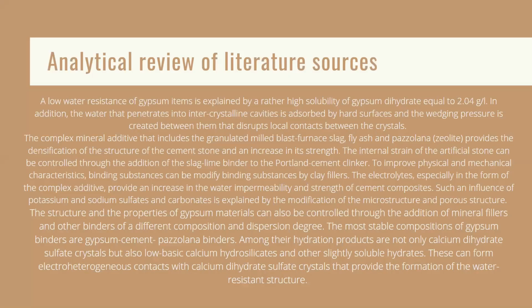A low water resistance of gypsum items is explained by the high solubility of gypsum dihydrate, equal to 2.04 g/l. In addition, the water that penetrates into intercrystalline cavities is absorbed by hard surfaces, and the wedging pressure is created between them that disrupts local contacts between the crystals.